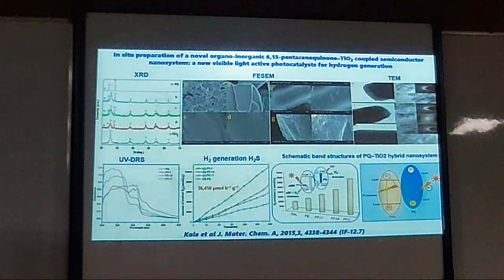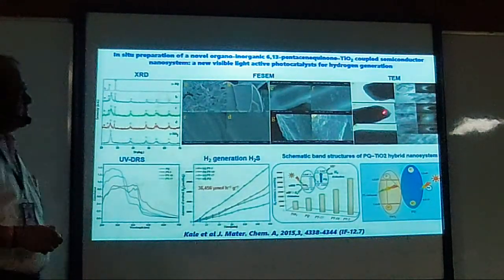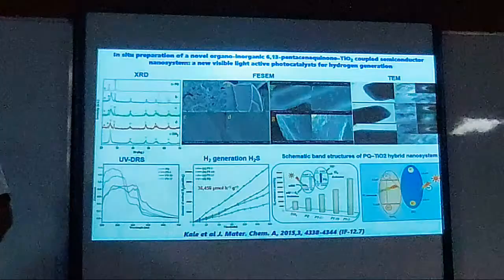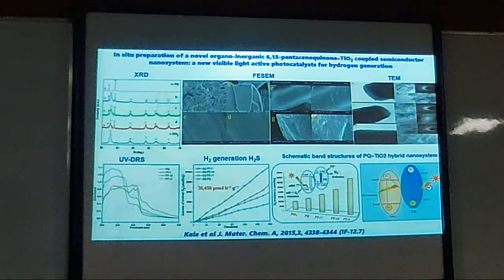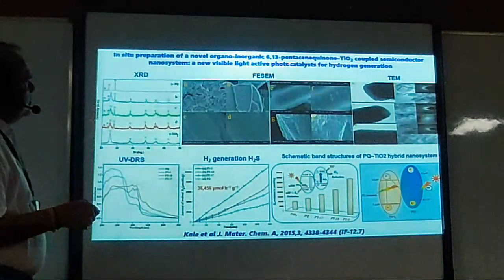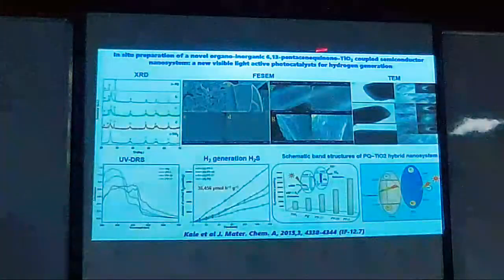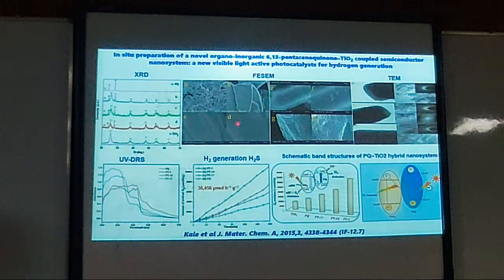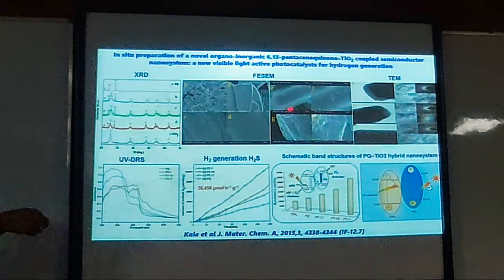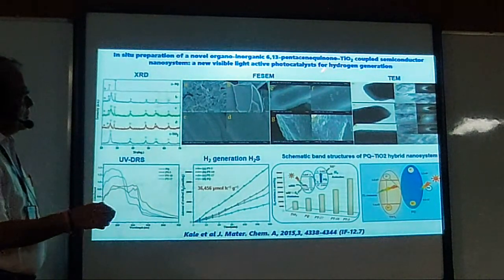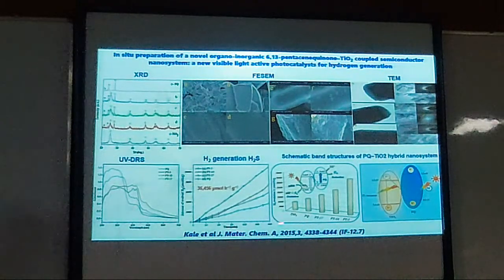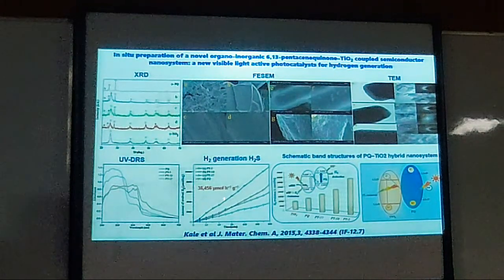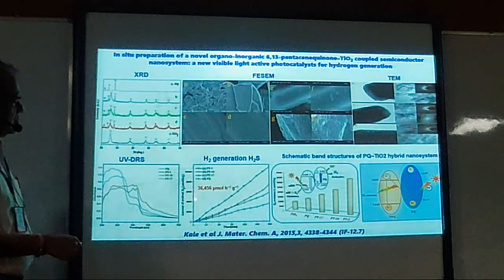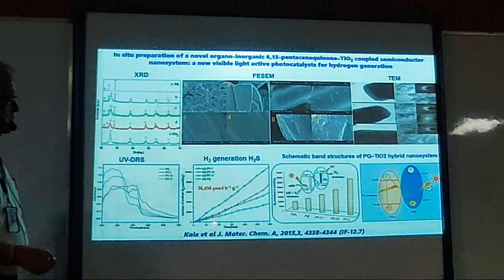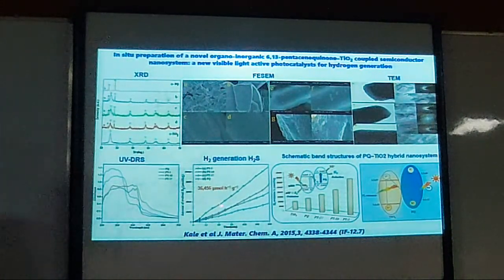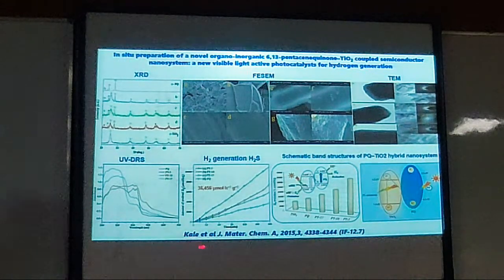One more new thing we did was to see whether, instead of having inorganic components, we can have organic molecules. This is an organic molecule, 6,13-pentacenequinone, and we coupled it with TiO2. We found that when we have a decoration of TiO2 on these nanoplates of pentacenequinone, there is a great enhancement in the hydrogen evolution. The maximum hydrogen evolution, like 36,400 micromoles, means almost 2 to 2.5 liters per hour, we got with this system. So we published in JMCA.